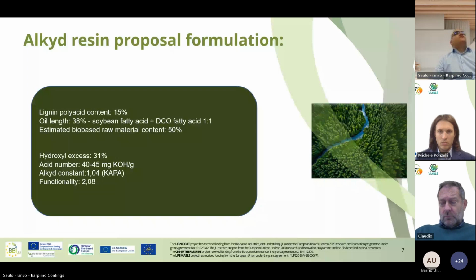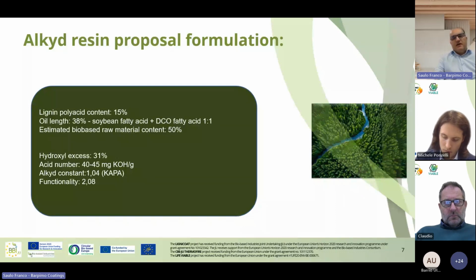So we introduced 15% of lignin in the polyacid content. The oil content of the alkyd was a short oil content, 38%, with a mix of soybean fatty acid and DCO fatty acid. This combination is because we achieved better properties. And the estimated bio-based raw material content in this case was 50%. We could increase it if we decided to use other bio-resources for polymers. For example, we know that there's pentaerythritol from bio-resources and other polyacids also from bio-resources, but we decided to focus on a classic formulation. And we established a hydroxyl excess of 31%, an acid number of 40-45 mg KOH/g, an alkyd constant of 1.04, and a functionality of 2.08.